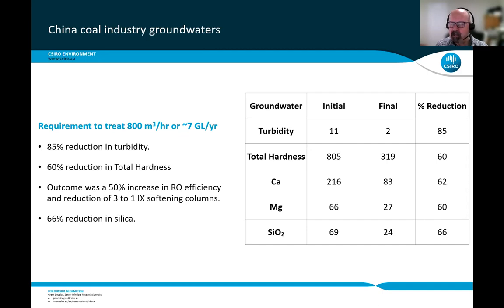And that was absolutely a fraction of the cost that it would take to build that additional RO plant capacity at site. And the other thing is that they had some softening columns, some ion exchange softening columns at the start of the process. Following the in situ layered double hydroxide treatment, they were able to reduce those from 3 to 1 operational ion exchange column.